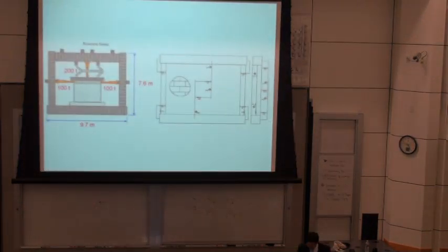This is a setup from Romania, which is a very old setup and is not commonly used anymore. It's also to simulate a fixed boundary condition for the cyclic shear test. In this case, you have your moment middle point in the middle and not at the top. So in order to simulate fixed boundary conditions, you have a parallelogram at the top in order to keep the head of the wall parallel.